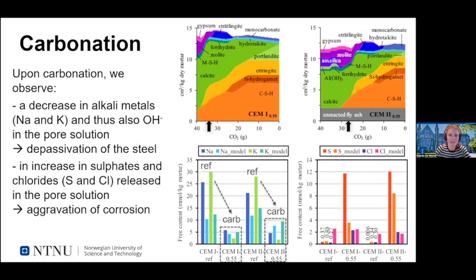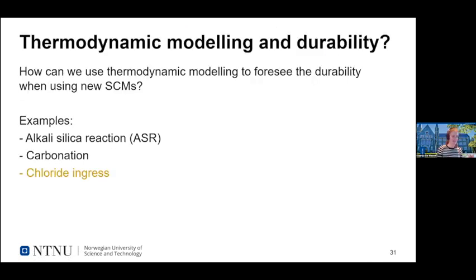Then a more striking thing was that we observed that upon carbonation, we got an increase in sulfur and chlorine in our pore solution. And that was both measured and predicted. And having an increase in sulfur and chlorine in your pore solution will actually aggravate your corrosion. And that's a parameter which is important to be aware about. Though in this case, we didn't see a very clear difference between the two binders investigated, but this might be very relevant for new SCMs, which potentially have more sulfur or chloride available and might affect corrosion rates in carbonated concrete. So this was an example on carbonation and how we use thermodynamic modeling to get a better understanding of the mechanisms.